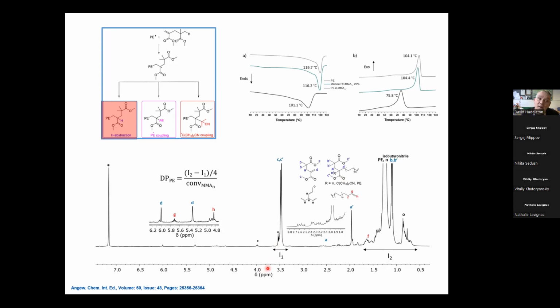And one of the things I'd say at this point is that's actually not necessarily a bad thing, because many of you will work on living radical, RAFT, ATRP, maybe nitroxide, and it's quite sobering to think that of all the polymers that are on your desk or in your room at the moment, 0 of them will be made by living radical polymerization. However, radical polymerization and non-living radical polymerization is all around you. Living polymerization, there'll be some of that on your desk, but that'll be made by living anionic or living cationic. So even though living radical polymerization has served me very well in an academic career, from an application point of view, it's disappointing, and actually we have to admit it has been pretty useless really in making stuff. Whereas if I'm using a free radical process, that's really what we need to do to get it into our lives.